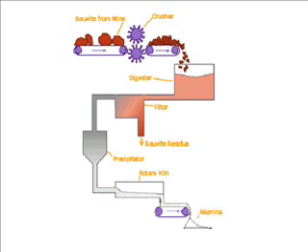Then this clear sodium aluminate solution is pumped into a huge tank called a precipitator. In this tank, fine particles of alumina are added to seed the precipitation of pure alumina particles as the liquor cools, resulting in a more solid powder-like substance. As the particles sink to the bottom of the tank, they are removed and passed through basically a dryer at an extremely high temperature to drive off the chemically combined water. The result is the fine white powder of pure alumina.